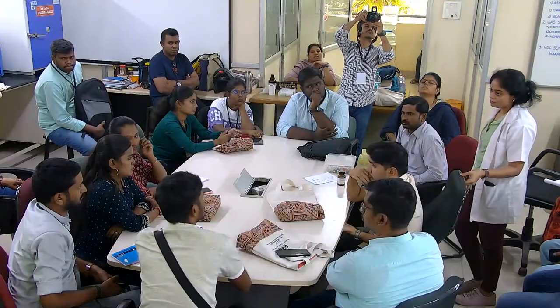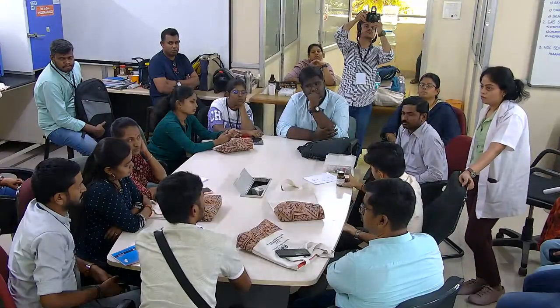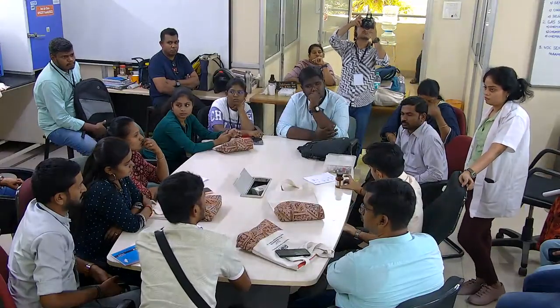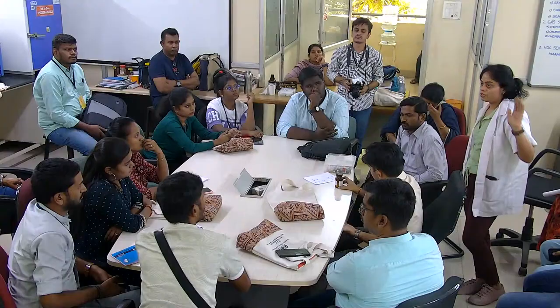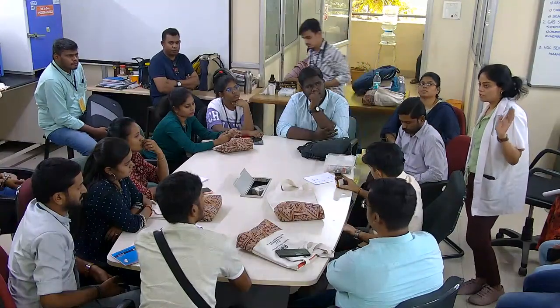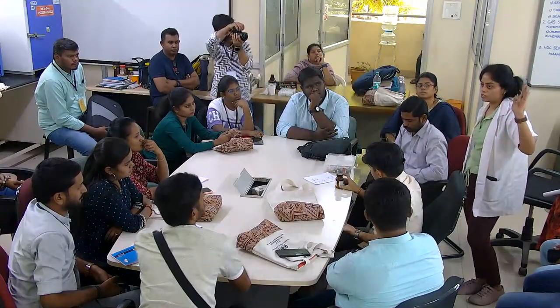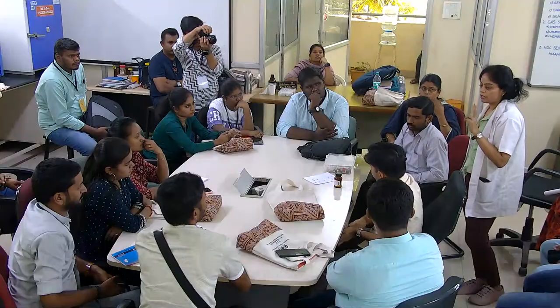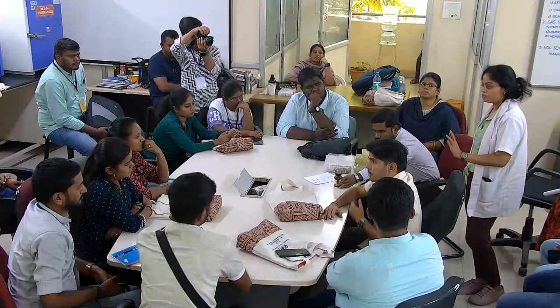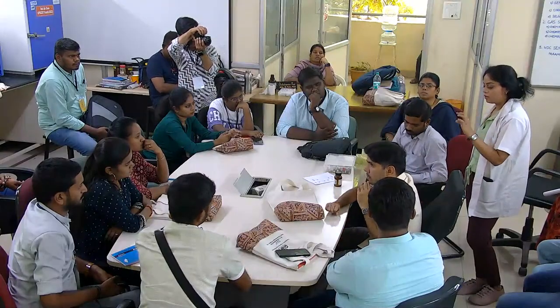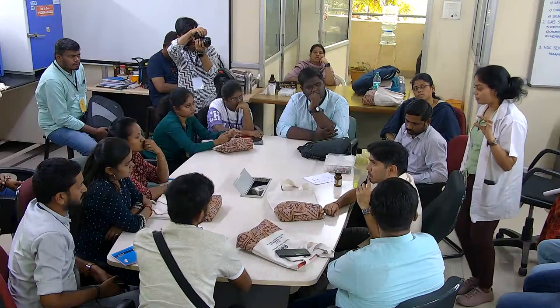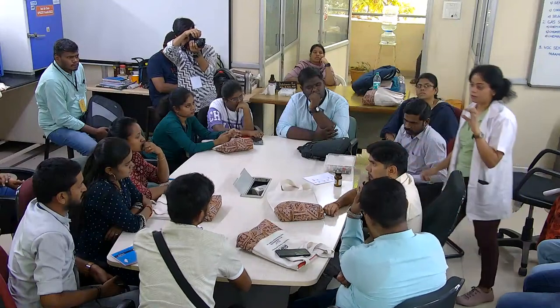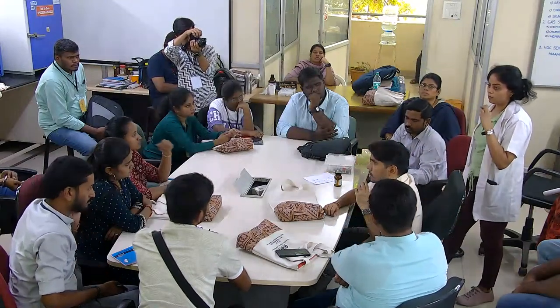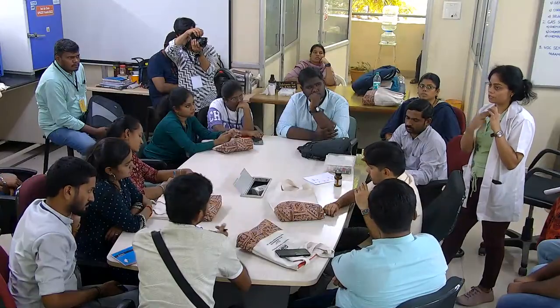After adding the chitosan component, you take that substrate. First, I'm preparing the material using the chemical co-precipitation technique, with these precursors called acetates and sodium hydroxide as the reducing agent. Now I take this material and add this sequence of ratios. If I'm taking 1 gram of copper oxide, I'm adding 2 grams of 5% chitosan and I'm probe sonicating.